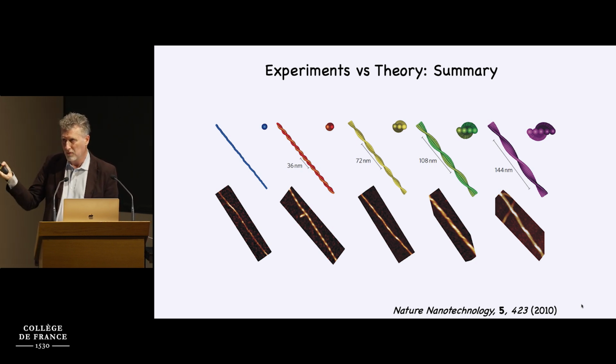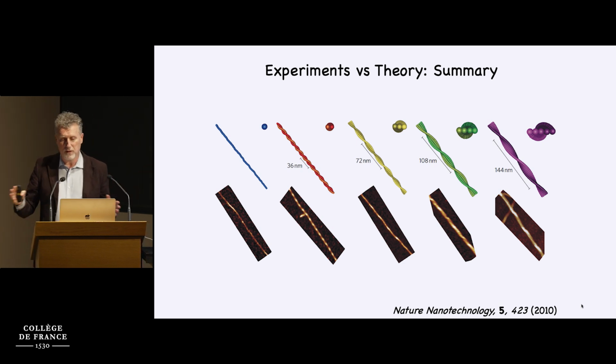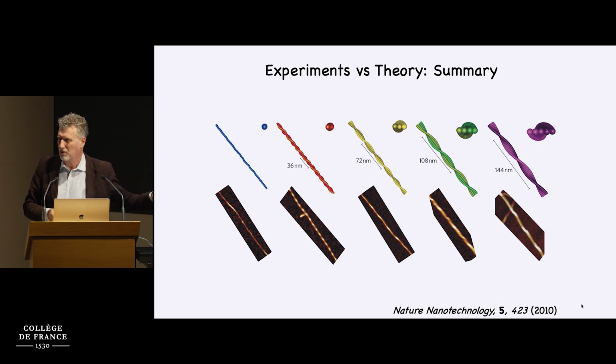So the angle of the twist is constant, and because of that, even if you break down this fiber, even if it is polydispersed, the twisting power is the same. So they have very spectacular liquid crystalline features, and they do form very controlled chiral nematic phases. And if I had more time, I could spend hours on this topic, which I will not do,